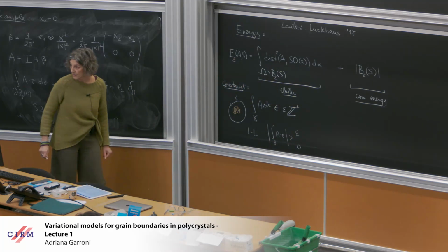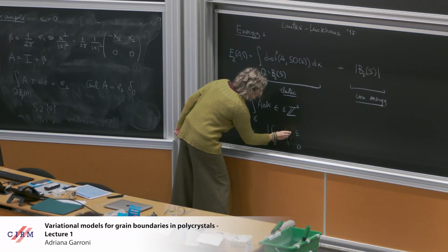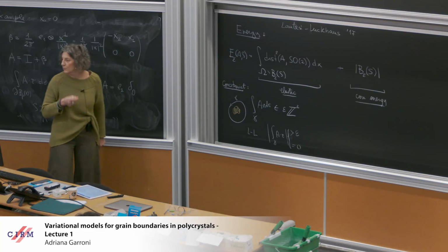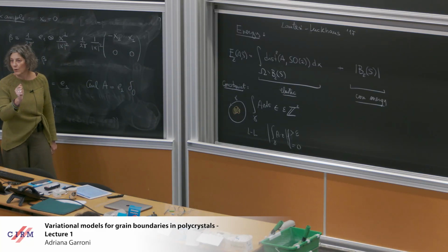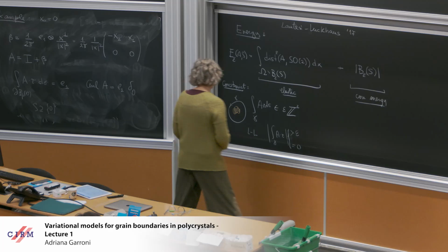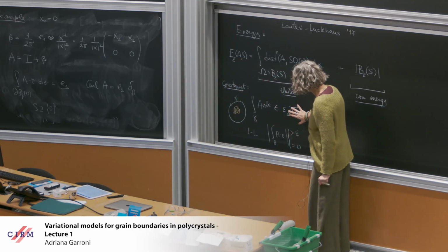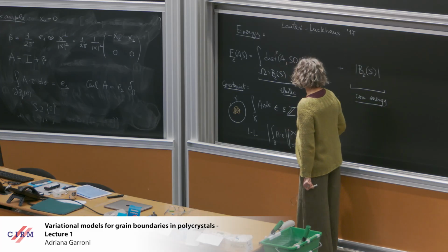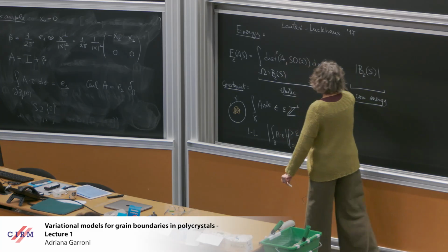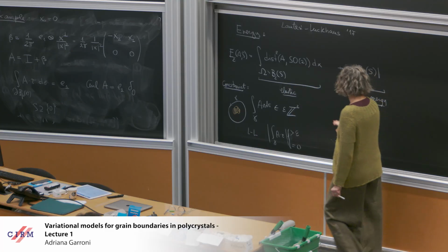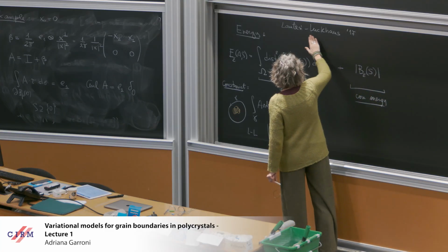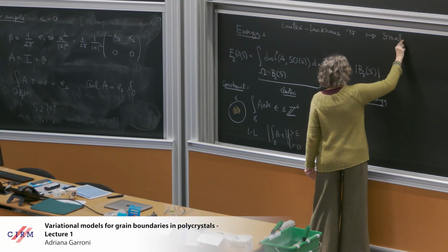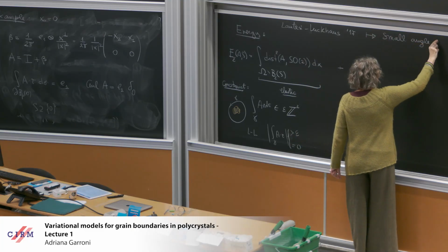Okay? So either you don't have incompatibilities or you have at least a quantum of epsilon. But if you make it more precise, somehow you describe very well the situation by assuming that the circulation should be a Burgers vector, so in the lattice, and the energy is made by these two quantities. And they introduced that just really in order to study small angle grain boundaries.